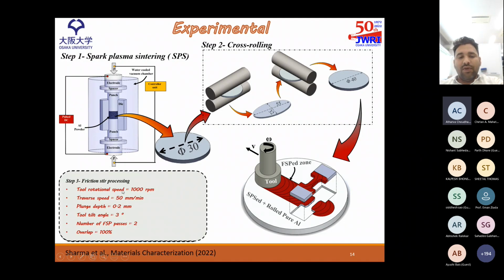So that's why we keep the temperature such that there will be a minimum heat input in the system, so that there are no interfacial reactions between the carbon, like graphene and CNT, and the aluminum to form aluminum carbide, because this aluminum carbide reduces the strength of the material. So that's why we designed the experiment in such a way that the overall heat input is very less in the system.